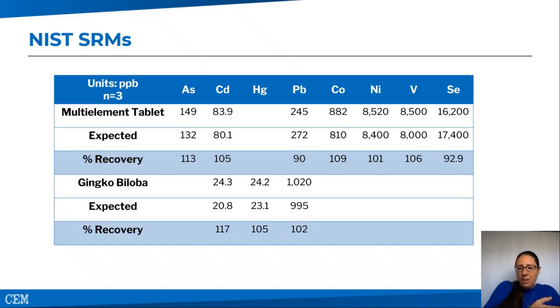And then we had the elements that were qualified for that SRM. We're looking at the data for those. There were more elements in the multi-element tablet for qualified values than there were in the ginkgo biloba. The reason we're putting those expected concentrations there is because I want you to note that there's quite a big range here. As far as cadmium, we're at around 80 ppb. And if we look all the way over to the selenium, we're at 16,000, right? So there's quite a big range here of what potentially could be in these samples that we're looking at. And so that matters, right? What's your dynamic range? What's fit for purpose for your method? I just want to show here that we're covering quite a big range for the methodology that we're looking at here today.